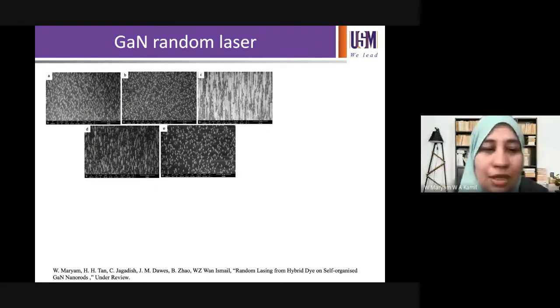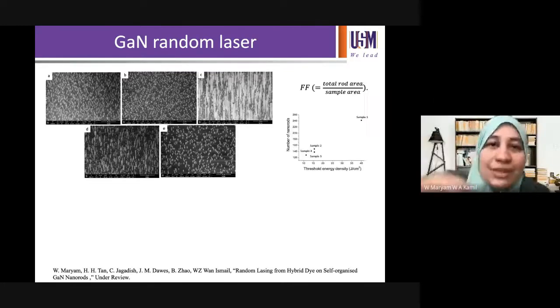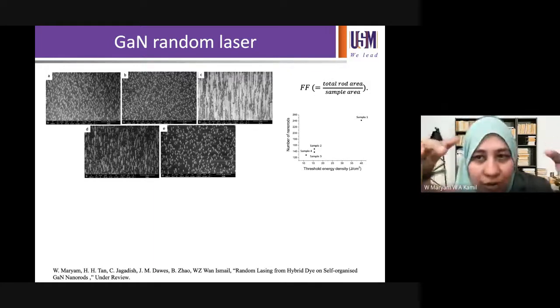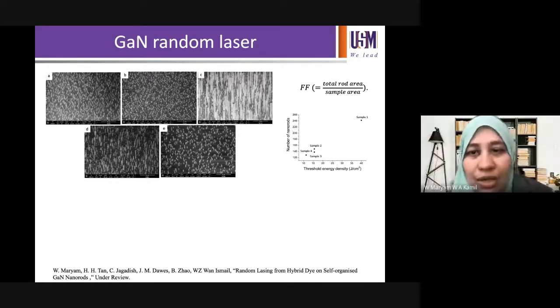And this is still under review, but I will share with you what we got. So these nanorods were self-organized, meaning that they did not have any masking in order to make them. Okay, so what we noticed is that when we calculated the filling factor, which is the total rod area divided by the sample area, we see that there's a change in threshold energy density. Okay, so there is a specific number of rods that you need to actually get low threshold for random lasers to occur.